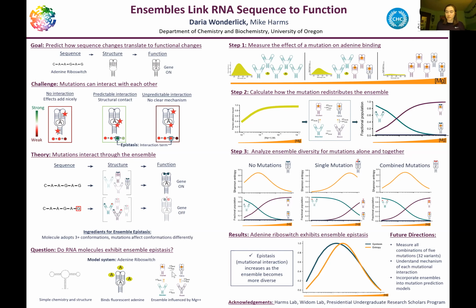And then next, to calculate how the mutation redistributes the ensemble, I use the fraction of bound adenine from the fluorescence measurements as an indirect way to measure the ratio of the adenine bound conformation. And so fitting this data to a thermodynamic model of the ensemble allows me to determine the ratios of the remaining conformations, which I'm showing here in their associated colors. And then finally, I can analyze how the mutations redistribute the ensemble when they combine. So then from these conformation ratio plots, I can calculate the amount of ensemble diversity with a quantity called Shannon entropy, which I'm showing here in orange. And mutations change the magnesium level at which the ensemble exhibits its maximum diversity.